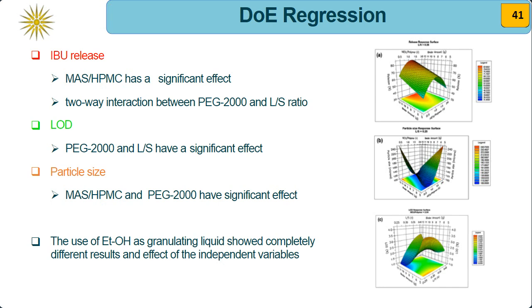The same experimentation was repeated by the same group, where this time ethanol was used as granulation liquid, and the regression of the DOE showed completely different results and effects of the independent variables. So we can see that the granulation liquid also has an important effect on the formation of the granules.